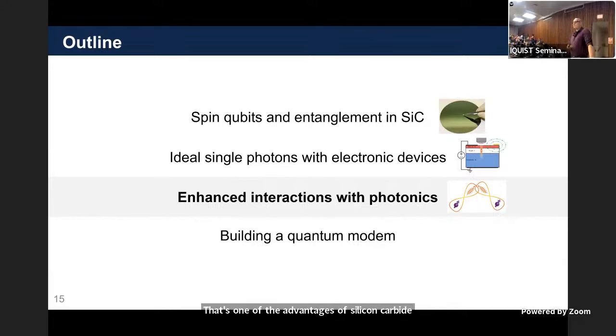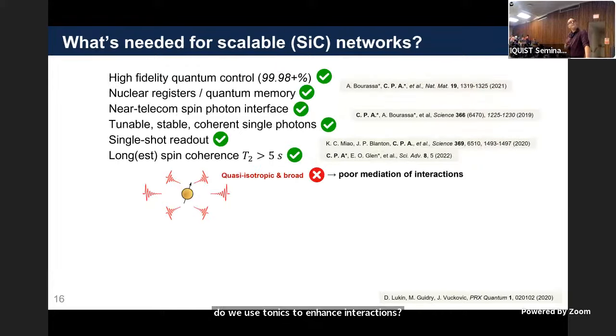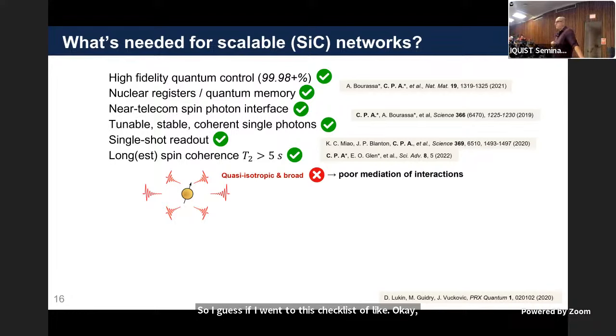So I'll now move on to this idea of how we use photonics to enhance interactions. If I went through this checklist of what's actually needed to realize your dream, we've gone through over the past 5-10 years and really hit a lot of our check marks, which is really, really exciting. We have high fidelity control. We have these long-lived nuclear spins. We emit in the near infrared or near telecom for low loss. We have these tunable, stable, coherent single photons. We have single shot readout. We have the longest coherence ever measured, which is great.